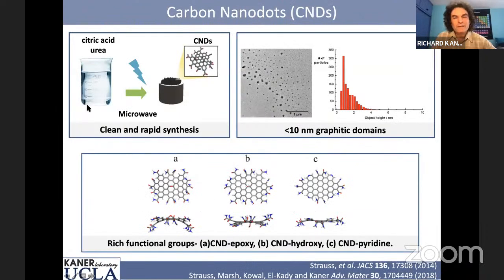So the way we can speed this up is we've been looking at the effect of carbon nanodots and how they interact with graphene. In a carbon nanodot, there are many ways to make them, but one of the simplest is you can take citric acid and urea and heat it in a microwave and you'll get a carbon nanodot. And here you'll see a whole lot of dots that we've gotten. They're all less than 10 nanometers of graphitic domains. And in fact, they're centered around about 1 nanometer, but there is some distribution, as you can see from this.